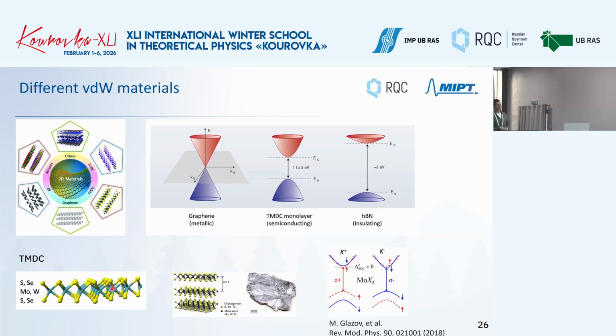And a very important thing regarding the optical properties is the following: when you go to the monolayer regime, it becomes a direct bandgap semiconductor, which means that you can use this for optics and for different optical properties of materials if you study this one monolayer. So there's a very nice review by Mikhail Glazov and co-workers discussing the mechanisms, what's going on, how the light interacts with the material. Very interesting. So the only thing to remember is that it has a direct band gap in the monolayer regime.